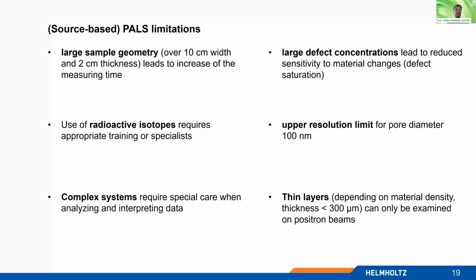If your system is quite complex, the analysis is also complex, but this is the case for all other methods as well. As I said, we have an upper resolution limit for pores, which is approximately 100 nanometers. And the last point is that for the source-based positrons, thin layers can't be investigated. So there is a limit of about 300 micrometers and lower. So be aware that if you would like to investigate thin films, you need another kind of positron method, which I will show you now.